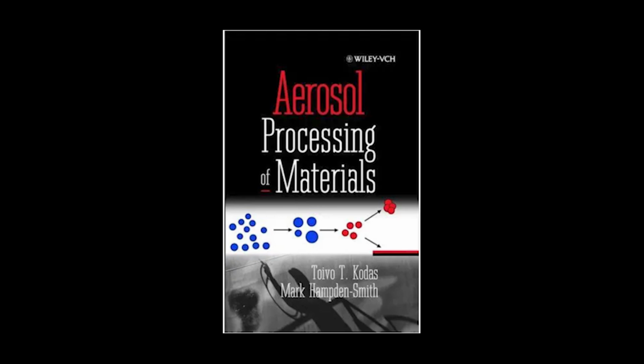So if I'm in the transport-limited regime, the rate is proportional to dp. Larger particles grow a bit faster, but in the surface reaction-limited regime, the rate is proportional to dp^2. Larger particles grow quadratically faster. That's a massive difference. It's the key to control. If you want to maintain a monodisperse aerosol, you often want to avoid that dp^2 dependence because it causes the larger particles to just gobble up all the available material, which widens your size spread.